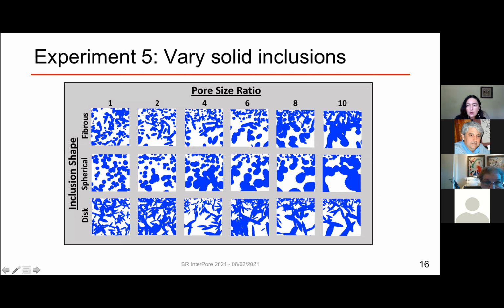One more experiment. We wanted to see, can we change the shape of the solid inclusions? So what we have here is fibrous, spherical, and disc-shaped inclusions. And here is the pore size ratio. So when the pore size ratio is 1, it means that the top and the bottom have the same pore sizes. So this really is a homogeneous material. And then from 2 to 10, we are increasing the pore size ratio from 2 to 10. And so you see clearly the differences in microstructure. Here we have fibers, spheres, and discs. Here there is no gradient. And then as you move to the right, you see an increase in the gradient of the pore space.